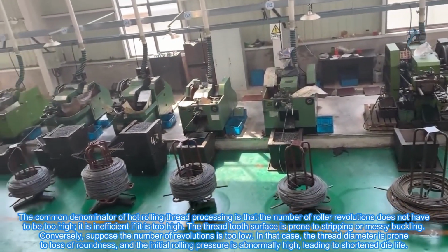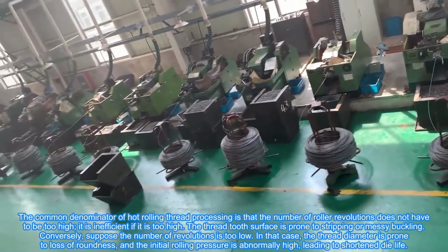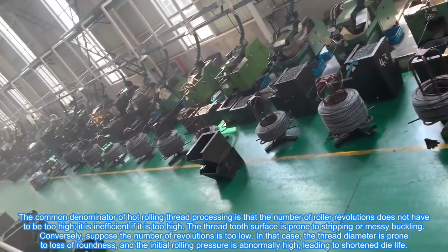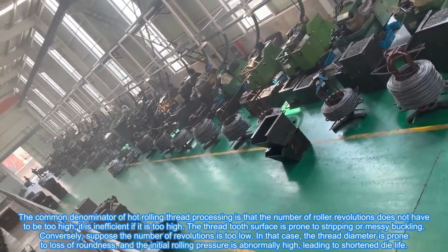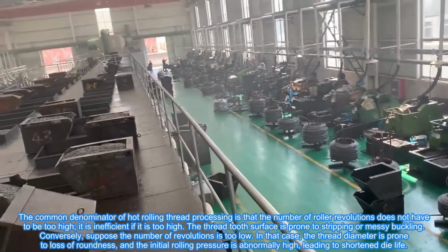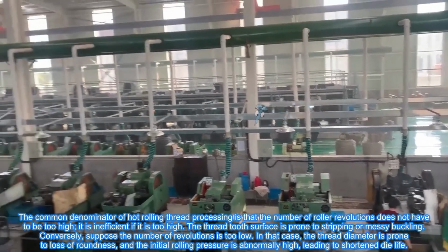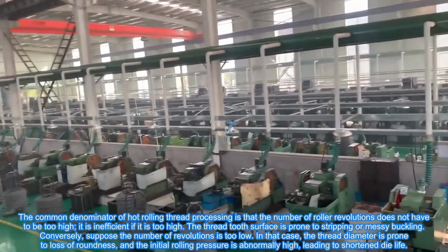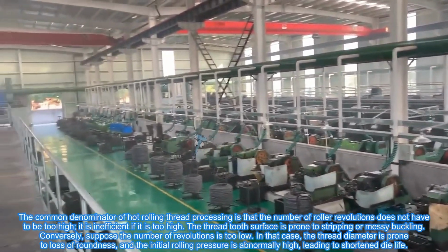The thread tooth surface is prone to stripping or messy buckling. Conversely, suppose the number of revolutions is too low. In that case, the thread diameter is prone to loss of roundness, and the initial rolling pressure is abnormally high, leading to shortened die life.